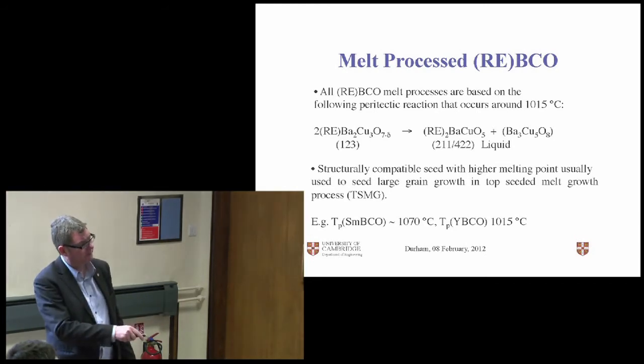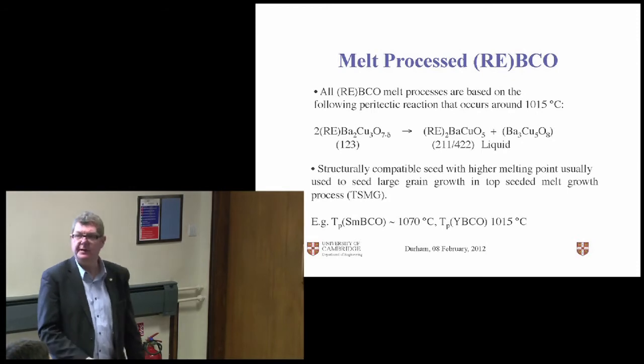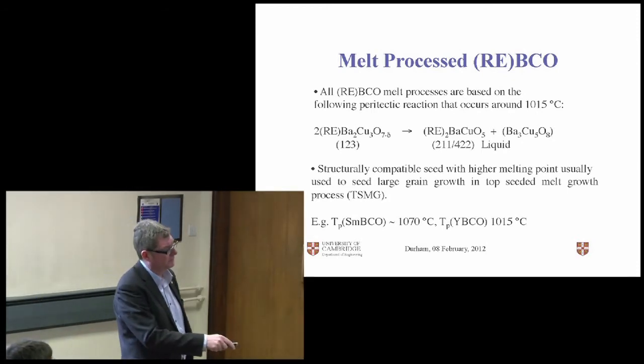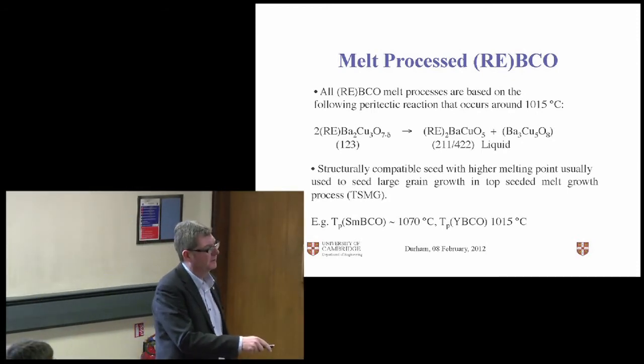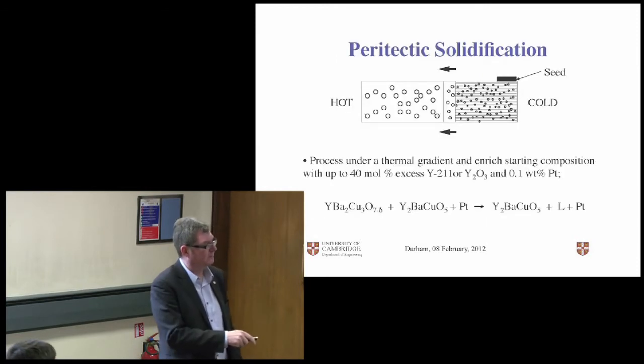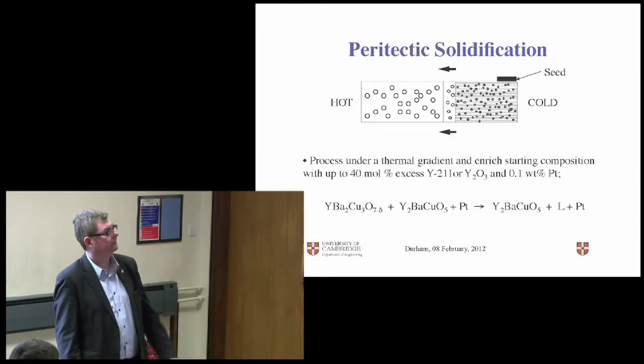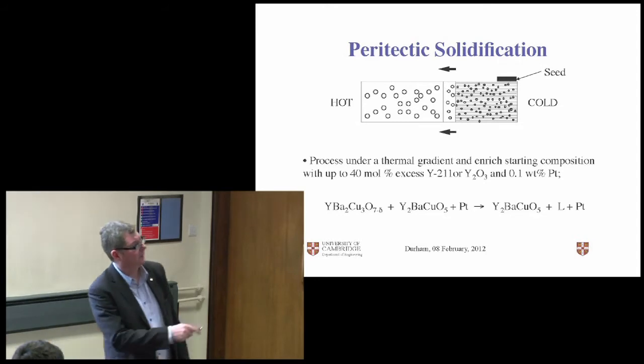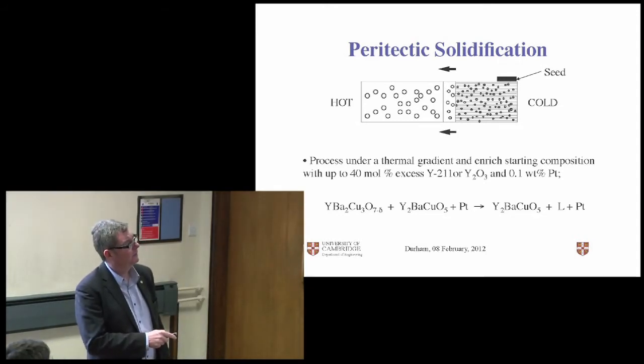So a suitable seed for YBCO is often samarium barium copper oxide. It's got a higher decomposition temperature, and that means we can partially melt a YBCO without decomposing the seed. It's slightly more complicated than that, but here's a schematic illustration of what happens. Here's our sample at high temperature, and we've added a seed here.